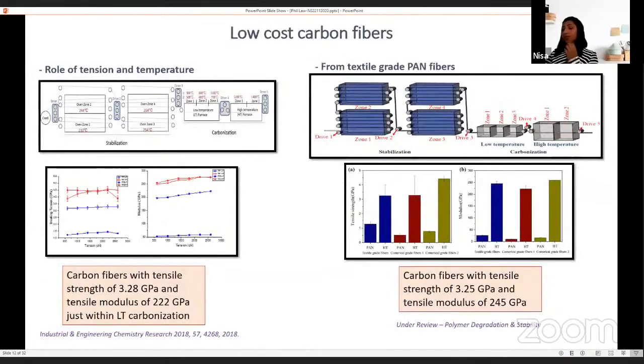We were also interested in making changes in the carbon fiber production line, or trying alternate precursor fibers, to come up with cost-effective ways to make carbon fibers. So in one study, we applied a higher tension by using a lower temperature in the furnaces, and we wanted to check the final carbon fiber properties. We found that we come up with automobile grade carbon fibers just in the lower temperature furnace.